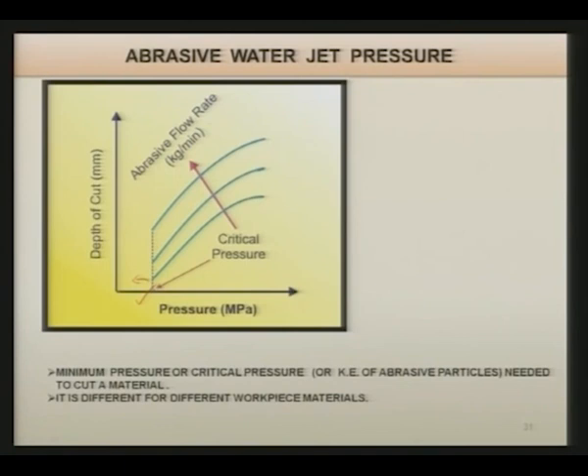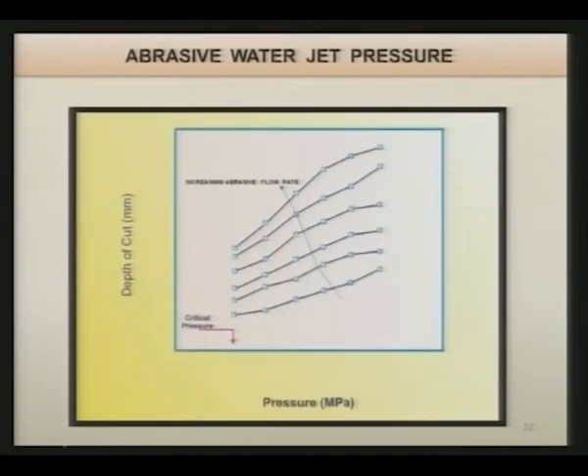pressure. Also, if you see here, as the abrasive flow rate increases, the depth of cut also increases, but again this is not a linear relationship. So, you can see here that a minimum pressure or critical pressure or kinetic energy of abrasive particles is needed to cut a material, and it is different for different workpiece materials. Same thing is shown over here with the various experimental points. As the pressure is increasing, the depth of cut is also increasing, and as the abrasive flow rate is increasing, the depth of cut is also increasing.